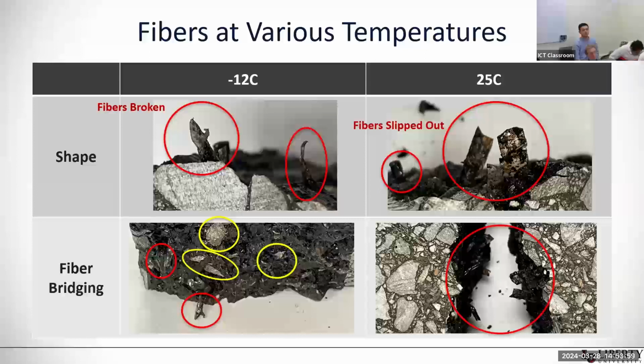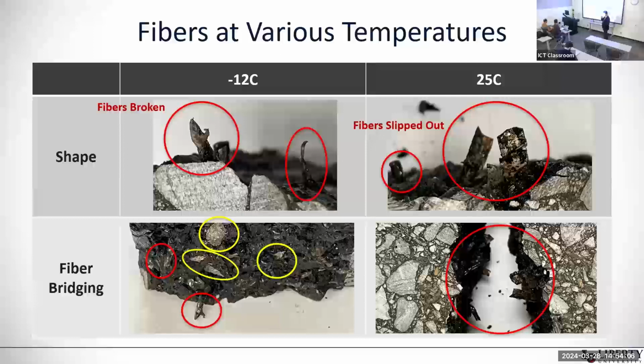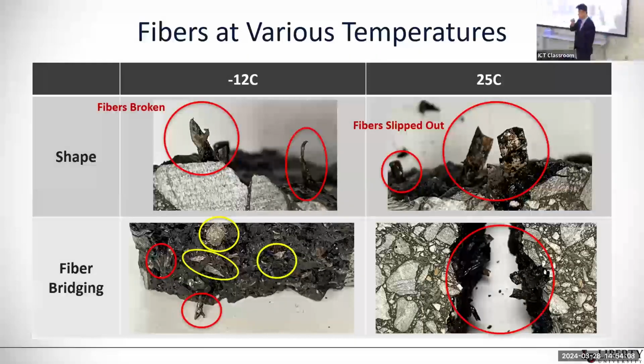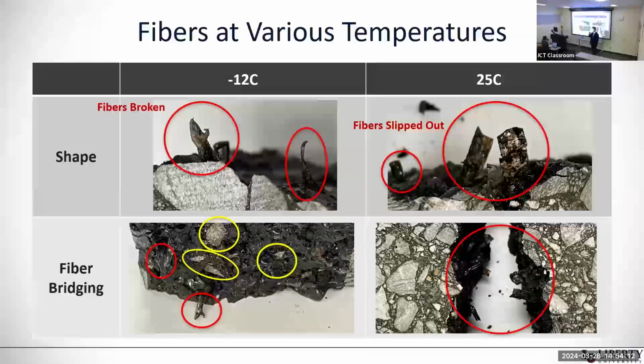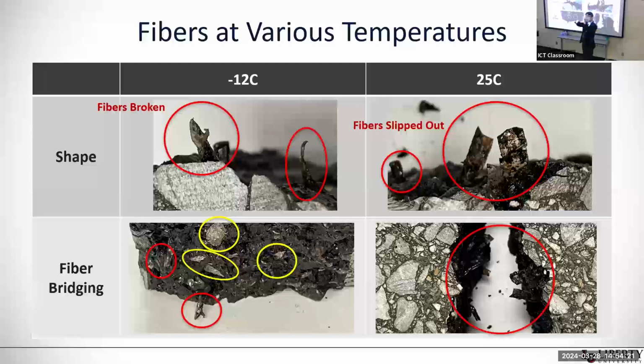Right. Yeah. So the first point: when we applied a high loading rate at -12 under the load line displacement control, we couldn't capture the data points post peak because of the sudden failure. We had just two or three data points, which doesn't show a good curve at the peak. So we couldn't capture that, and that's why we adjusted the loading rate to capture that part. And also the second one,